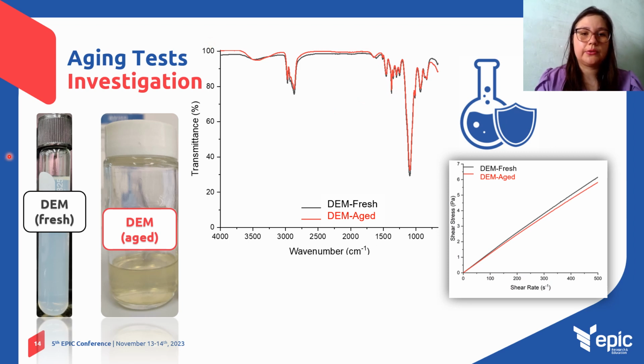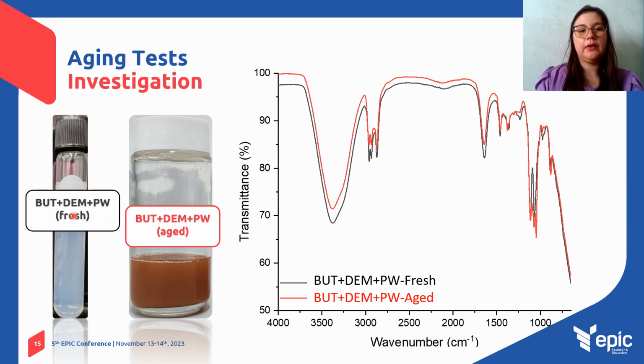the aging conditions. However, when produced water enters in contact with the emulsifier, a brownish solid is formed at the aging conditions. Such a finding shows that if the brine enters in contact with the chemical injection fluids, a brownish precipitate might be formed that could cause the blockage of the chemical injection valve's orifice, enabling us to elucidate if there is backflow in the valve. A brownish precipitate can cause the blockage of the valve, leading to a clogging issue.